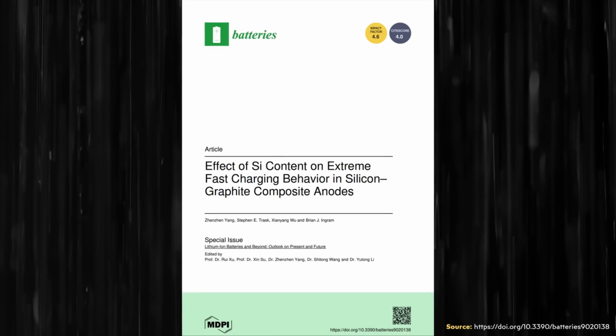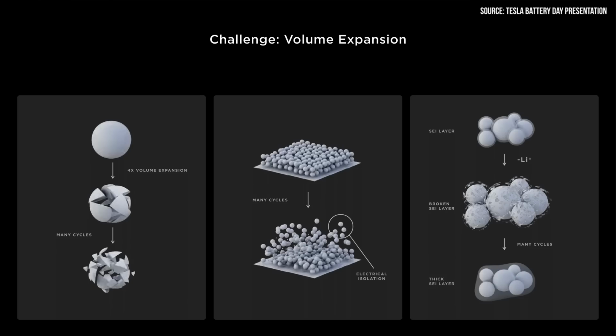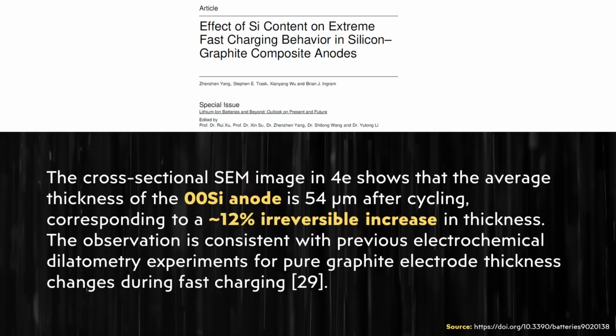Now, with that being said, this research paper also dealt with the expansion issues with silicon. Of course, no matter what mechanism you put in place, there still is going to be expansion of silicon. You just have to actually build a system to mitigate the damage from that. So when it comes to the battery expansion results in this research paper, they wrote here specifically that for the 0% silicon anode, there was approximately a 12% irreversible increase in thickness after cycling. So even graphite does have some expansion that happens.